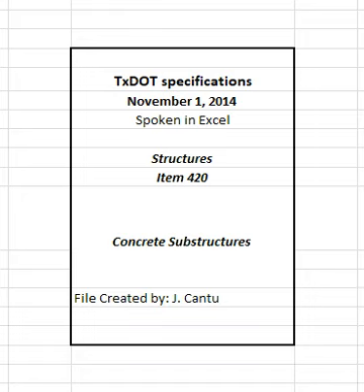4.7.9 Consolidation. Carefully consolidate concrete and flush mortar to the form surfaces with immersion type vibrators. Do not use vibrators that operate by attachment to forms or reinforcement except where approved on steel forms. Vibrate the concrete immediately after deposit. Systematically space points of vibration to ensure complete consolidation and thorough working of the concrete around the reinforcement, embedded fixtures, and into the corners and angles of the forms. Insert the vibrators vertically where possible. Vibrate the entire depth of each lift, allowing the vibrator to penetrate several inches into the preceding lift.